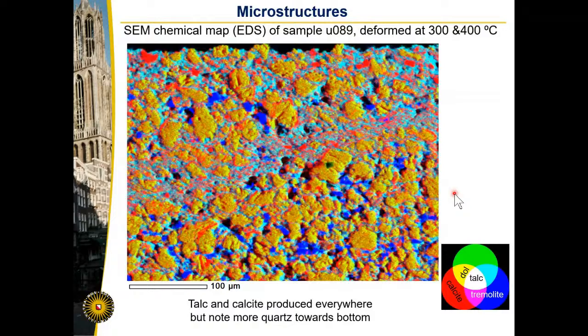Now, this is the sample that was deformed at 400 degrees as well as 300 degrees, and this is quite a spectacular microstructure, if I say so myself. And you can see clearly that there is calcite being formed. You can see that it's forming very localized in this shear band as well as in a matrix. There's still quartz that is left over. There is a lot on this side. There's no quartz on this side, but there is a lot of calcite and a lot of talc.